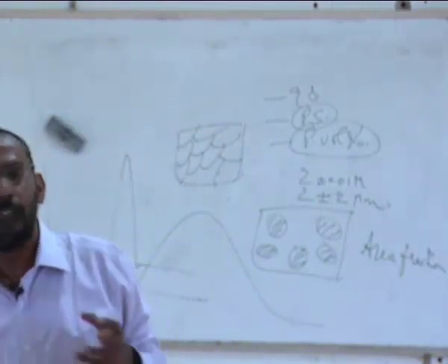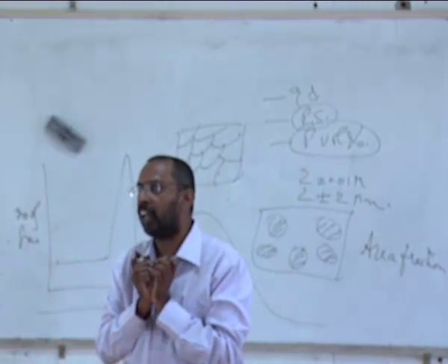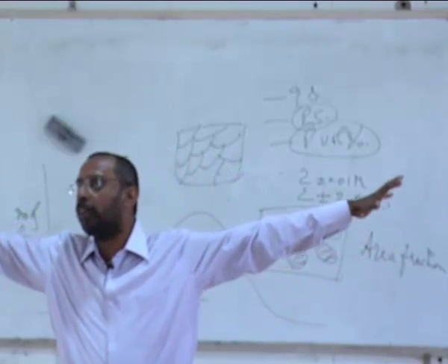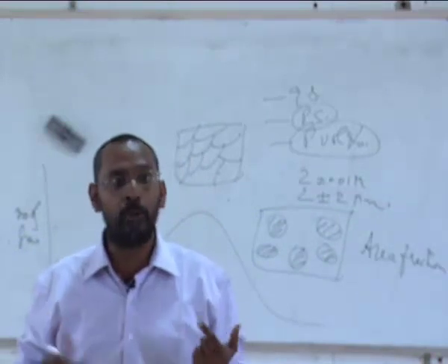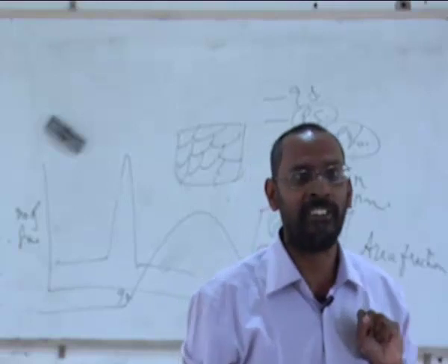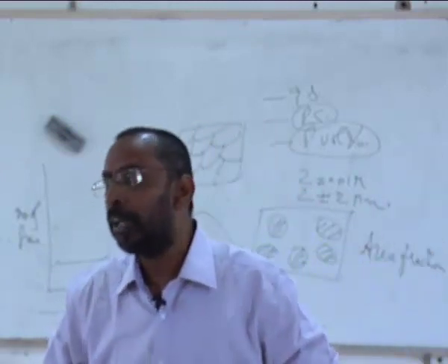And if there is a reasonably uniform distribution of these precipitates, uniform in size. For example, if there are very big particles and also a few very small particles, and the region where I am looking may have only big particles, another region may have very few, very small particles, then this may not be correct. But at the same time, because I am seeing a large number of regions, getting an average area fraction, that average area fraction can be equated to average volume fraction, provided the particles are spherical in nature. But if the particles are elongated in nature, then this is not true.